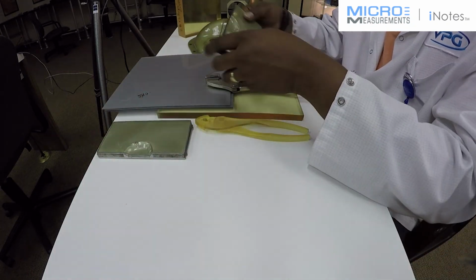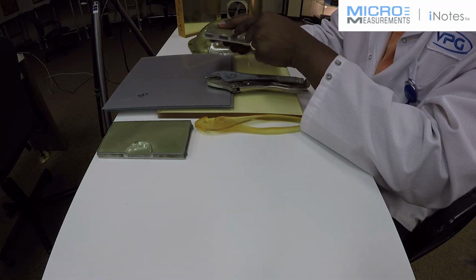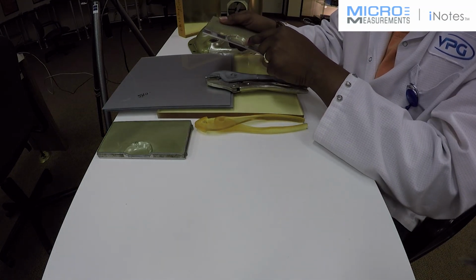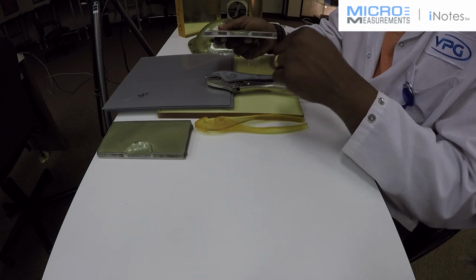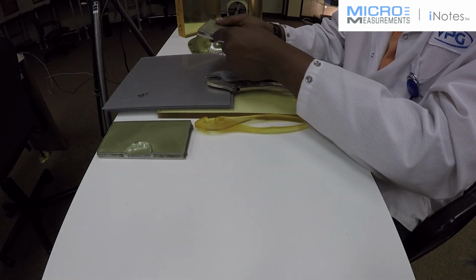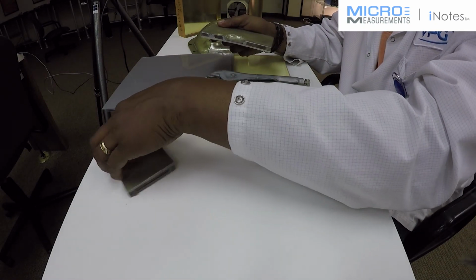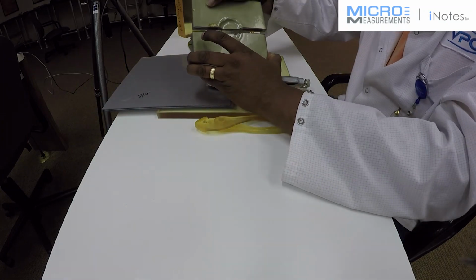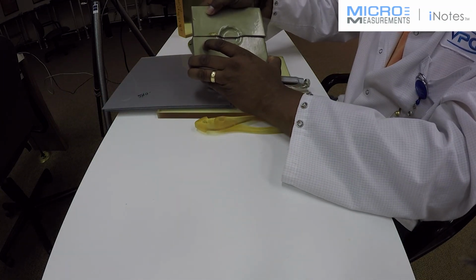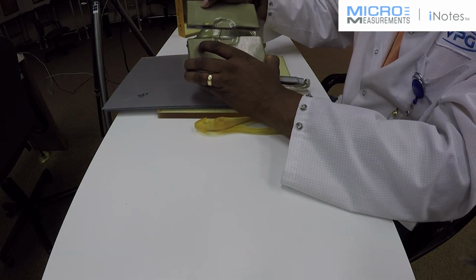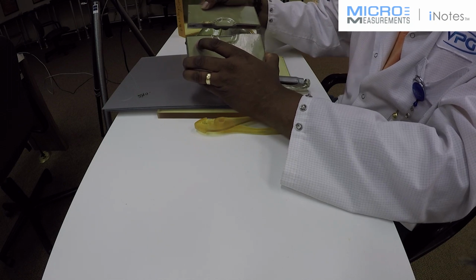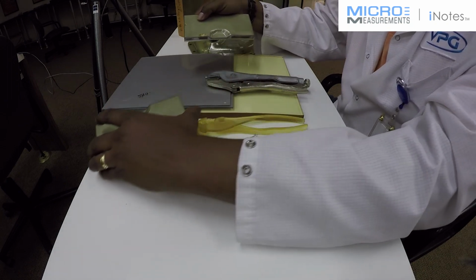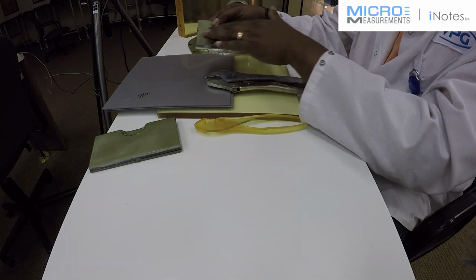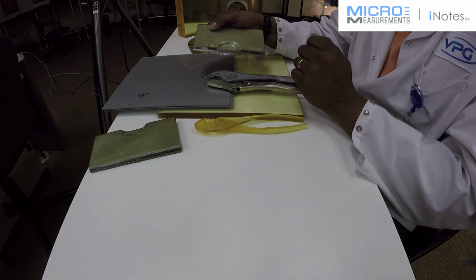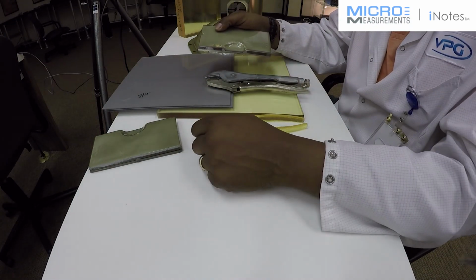We can also do residual stress measurements with this technique. In fact, I've got a part here that has been welded, and this is the welded area. To get to the residual stresses, we simply need to section the part, which we have done. Part two of this is here, and we cut right through the middle to relieve any residual stresses that might have been created from the weld. The PhotoStress technique would then show us through this optical sheet how much stress was actually there after the weld was done.